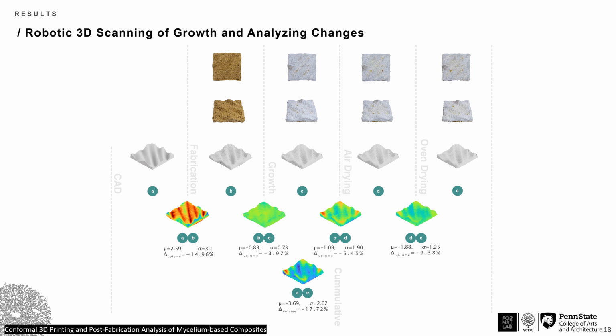As illustrated by the comparison of the BC pair, the change during the growth phase was minimal and uniform. Here, both the mean and standard deviation values were the lowest among all other stages we analyzed. During the air drying stage, however, we observed a reversal of this uniform shrinkage behavior. The comparison between the CD pairs illustrates the spatial distribution of these changes, signifying localized changes around the corners of the panel. The oven drying stage followed a similar trend and presented the highest rate of shrinkage, with nearly 10% volume loss from the air drying stage. And cumulatively, we observed a total of nearly 18% of volume loss and observed significant deviations around the corners due to uneven loss of water content.